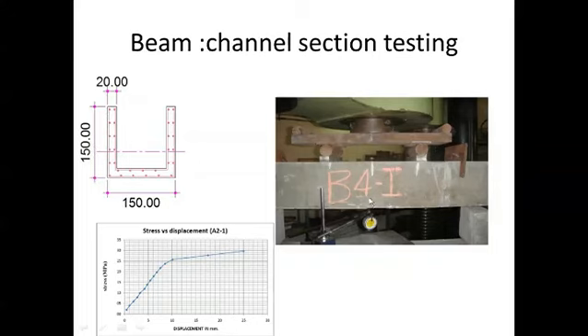The complete 3-meter full-scale beam was tested under 4-point loading, and we could reach a tensile flexural stress in the beam of almost 25 Newton per mm square for actual full-scale testing.